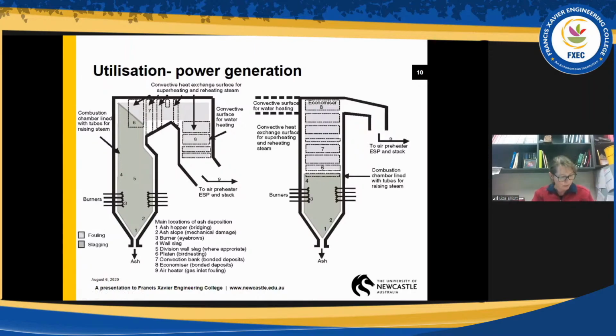So the thing to note about using coal in here is that it's a combustion process. That is, it's an oxidizing process. There's always excess oxygen, so the coal will always be looking to be burning out. The issue associated with this type of boiler is hotspots forming in the radiative section where the coal is burning too fast and that area gets too hot. And that can have big issues on the tubes, particularly the material that the tubes are made out of. If it goes too hot, they can be deformed and they can eventually leak, which is a disaster.